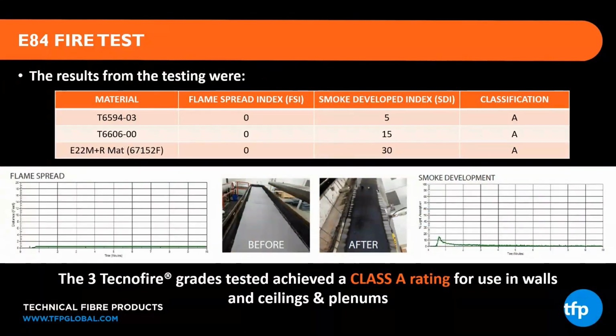So the first version in that top chart was T6594-03. That is a resin infusible grade. That was that gray fabric type material. If you look at the picture below, you can see the before and after. That shows the Steiner tunnel with the top off. So you can see our specimen. It's a 24-foot long by 2-foot wide specimen. And you can see the after effect.